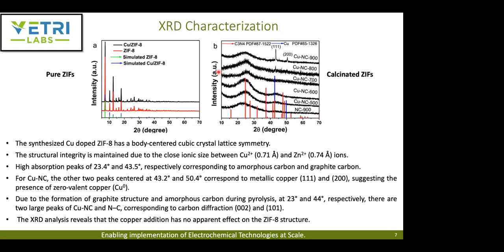And also for the copper with nitrogen doped carbon, they have two other peaks at about 43.2 degrees and 50.4 degrees, corresponding to metallic copper, Cu111 and Cu200. So this suggests the presence of zero valent copper. And then apart from the formation of this graphitic structure and amorphous carbon from pyrolysis, they also have two large peaks showing the diffraction of 002 and 101.